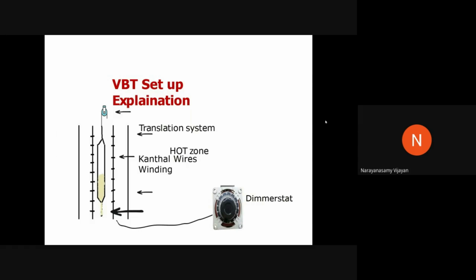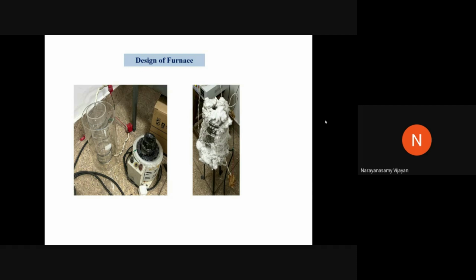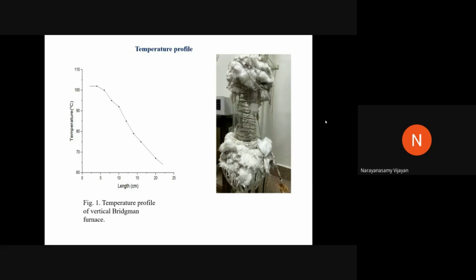Then after that, we connect the dimmerstat and slowly increase the power. Automatically the center portion goes to high temperature, while the bottom as well as the top portions always have lower temperatures. Sometimes when you put your crucible and hang it, the hanging medium depends on some metallic wires. Through those metallic wires, sometimes heat loss will happen. So what do we do? We normally wind some thermal wool thread around the metallic wires, in order to avoid temperature fluctuations from the top as well as the center portion.